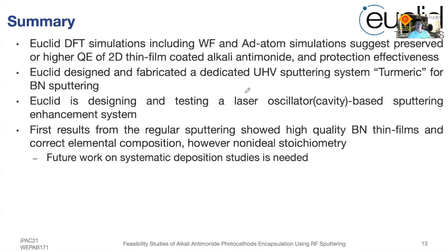First results from our regular sputtering, not a reactive sputtering, show that high quality boron nitride thin film and with the correct elemental composition can be achieved. However, the stoichiometry needs some further optimizations. And future work on systematic deposition studies is needed. We look forward to more collaborations with other institutions.